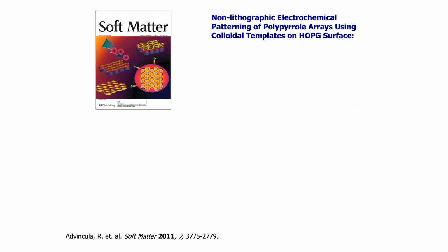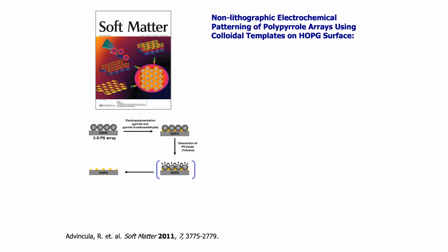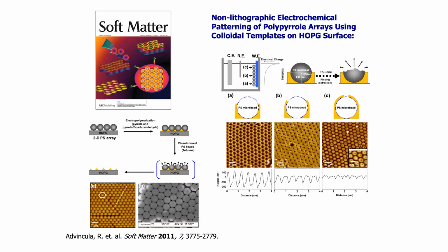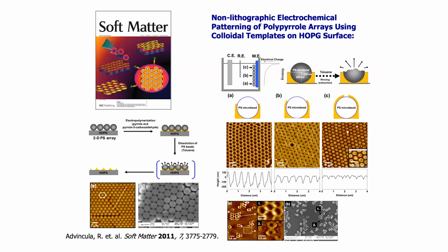In the past, we have demonstrated that latex sphere particles of polystyrene can be deposited on surfaces as two-dimensional arrays, which have a hexagonally packed structure as expected, to show very interesting templates for the electrodeposition of conducting polymers. In this first paper, we demonstrated that the potentiostatic deposition of polypyrrole on these templates results in beehive-like structures, half-dome and full-dome structures. These particles can in fact be harvested from these surfaces to produce micro or hollow shell capsules.